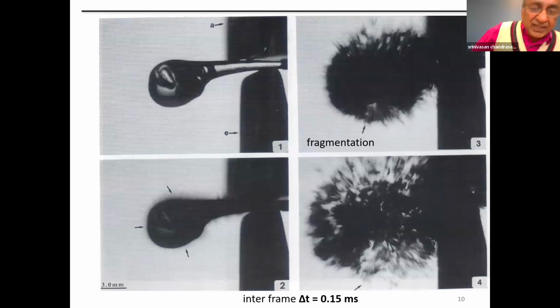So this shows a sequence of 4 frames. This is filmed at about 6,000 frames per second. So the time between frames is about 0.15 milliseconds. So you see a drop on the left, 1, 2, 3, 4 is the sequence of the frames. And then as you hit it with the chisel, the whole drop explodes, and this gives you sort of an overview of the explosion. So from this type of a picture, you can get some details like how fast the fragments fly out. You see that the explosion is spherically symmetric, very much similar to the first atomic bomb